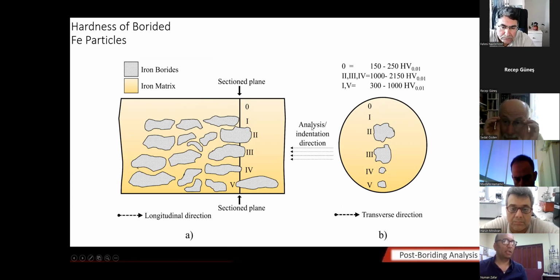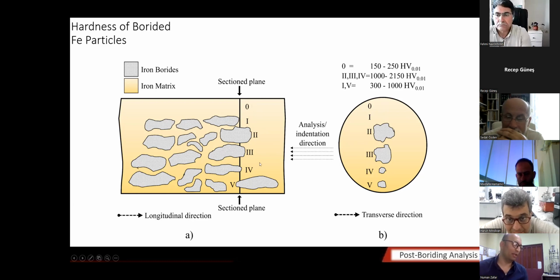This is the indentation analysis. You indent the surface from here. The appearance of 0 and 1 is the same, but one might have iron boride phases right under the polished surface which you have indented. So it might show a hardness which is higher. Such a thing is more likely to be witnessed in S10 specimens because they have a 50% borided and 50% non-borided region. 2, 3, and 4, no matter what you do, if you indent them, you will see a high hardness of iron borides. Why? Because they have supporting hard iron boride phases under the indented plane.